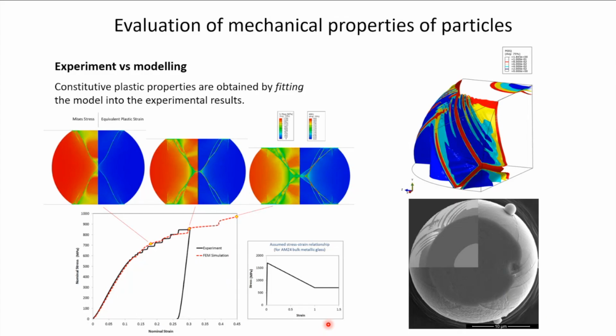That would be quite tricky if you want to do that during tensile testing because of the shear bands, the same phenomenon. They are unstable in plastic deformation and they break easily, so they show almost no ductility. But in compression it is different. But still, you cannot get the flow stress versus flow strain easily because, as I said, it's an unstable material under plastic deformation, unless you do something like this. So this is something that you wouldn't be able to see in any tensile testing, because as soon as you get a decrease of the flow stress with increase of strain, you end up with strain softening, and that's a recipe for rupture.